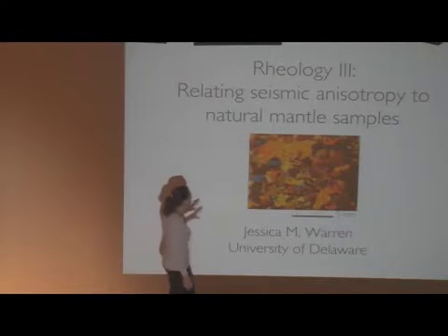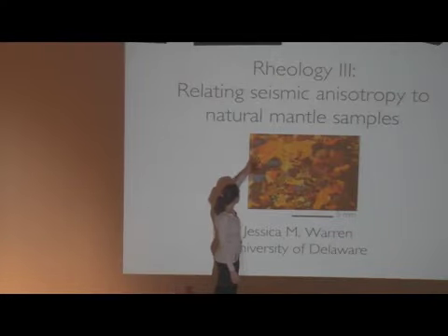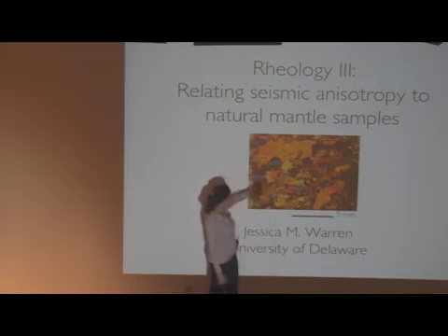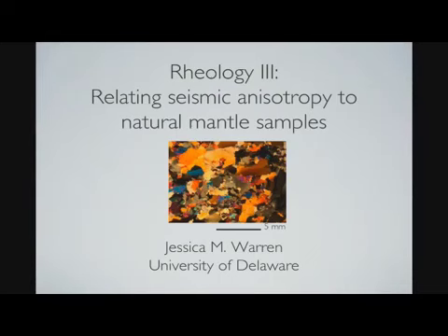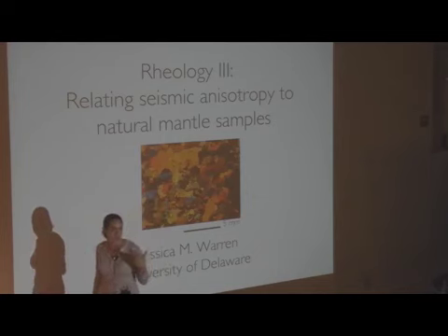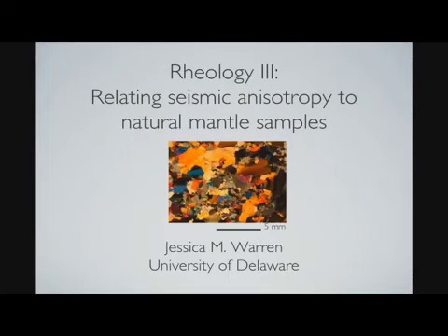But what I want to focus on in these samples today is largely the olivine, which is most of what you're seeing in this image. There is a little bit of orthopyroxene in this sample, and there are trace amounts of spinel that are not visible in this image. Olivine here, you will see this gradation in the colors. That is an indication of subgrain boundaries. That is an indication of the deformation that has gone on in the sample.